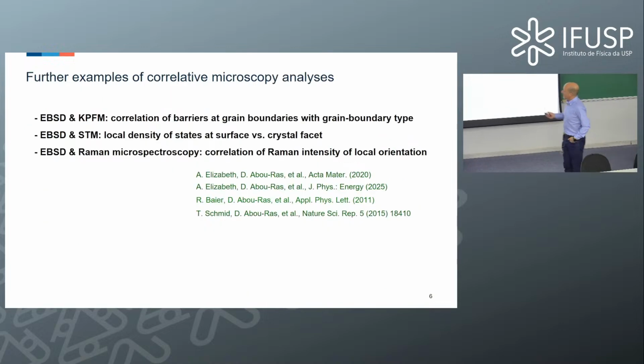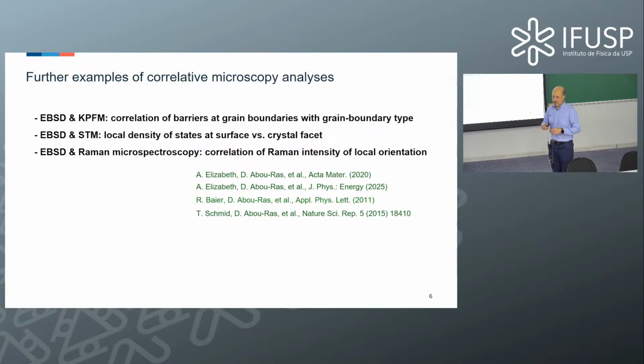There are a number of results which I skipped because I think it makes the whole talk too long. But I have collaborated with various colleagues working on Kelvin probe force microscopy or scanning tunneling microscopy, where we combine EBSD with scanning probe techniques. So we can correlate local orientations or grain boundary properties with structure, for example the work function difference at grain boundaries, or in the case of STM, we can learn about the local density of states or of facets, and so detect the density of defect states at certain facets. That's quite valuable information for various material systems.